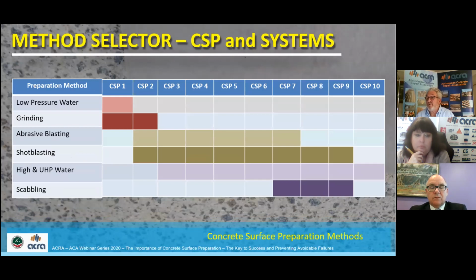Same chart, preparation method and what it'll achieve. Low pressure water will give us a CSP 1, grinding 1 to 2, abrasive blasting 2 to 7, shot blasting 2 to 9, high and ultra high pressure water CSP 3 to 10, and scabbling CSP 7 to CSP 9.